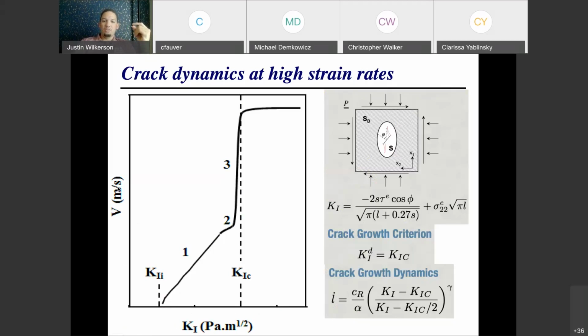Okay? And so what you find is that, and this is actually a log scale on the y-axis. And so when the stress intensity factor is low, you get a fairly linear line in log-log space, so it's a power-law relationship. And we call that stage 1 of the relationship between crack velocity and stress intensity factor. As you approach the K1C of the material, then the crack velocity shoots way up to very, very high velocities. Still fairly linear on this log-log plot. And then it tends to saturate out at an upper limit.